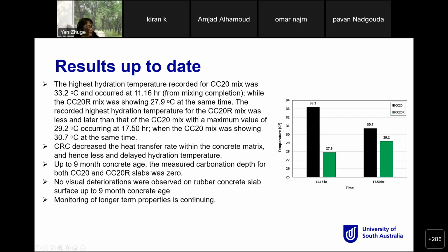So up to 9 months concrete age, the measured carbonation depth for both normal concrete and crumb rubber concrete was 0. And no visual deterioration was observed on the concrete slab even up to now. And the longer-term monitoring is still continuing and keeps going. So there are some good signs.